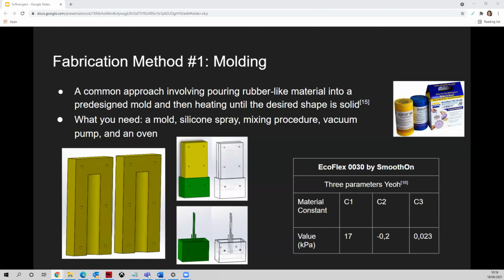So one approach is to pour the elastomeric material into the mold, as shown in these slides. And for this, you would need silicone spray, a mold, a mixing procedure, a vacuum pump to remove bubbles, and an oven for curing.